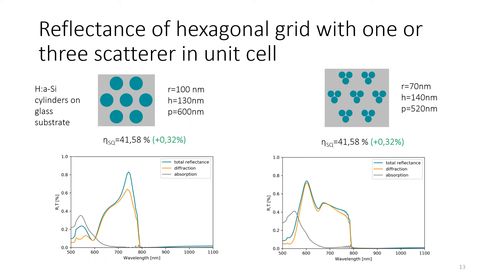We made several different designs; I'm showing two here. The first uses hydrogenated amorphous silicon cylinders on a glass substrate arranged in a hexagonal grid. The reflection is exactly in the needed range of 600 to 800 nanometers, and this is almost completely diffraction with only a small specular reflection component. A very interesting additional point is that above 800 nanometers there is essentially no reflection, so we effectively have a built-in anti-reflection layer. The Shockley-Queisser efficiency improvement with this design is 0.3%.